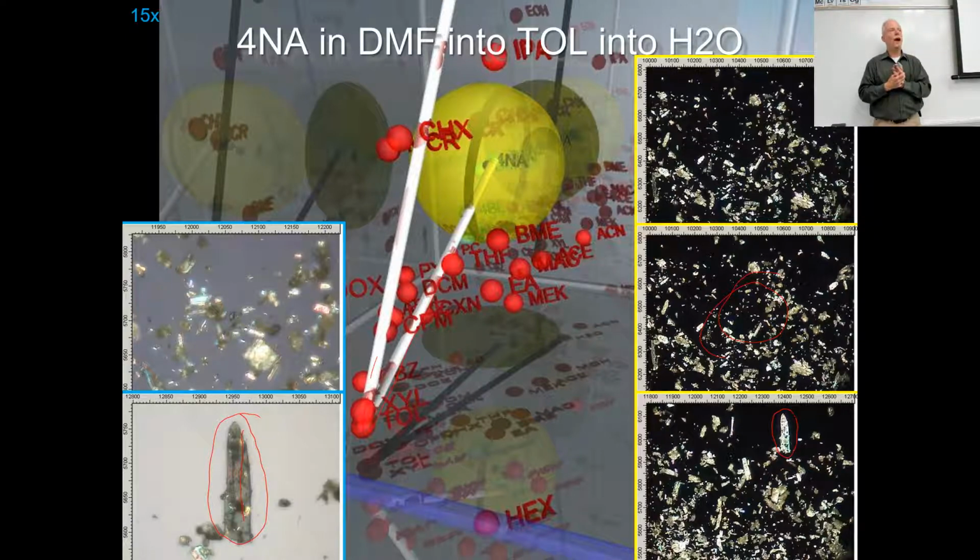When they brought that copper pot from the former facility and installed it in the new facility, they got the right morphology. I just want to take that little excursus to say, sometimes it's not just the chemicals that you put in there, it's the container. You need to always remember that, because the container has a Hansen solubility profile too. It has a D, P and H value, and that will change if it's not clean. So cleaning is important as well.